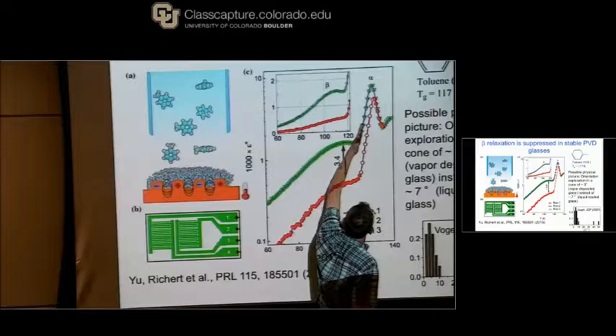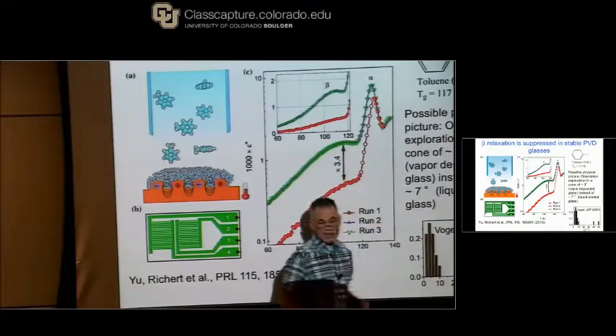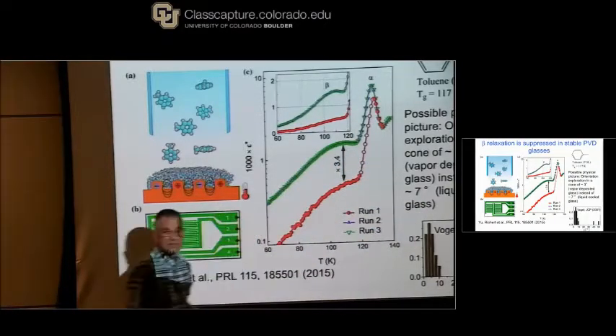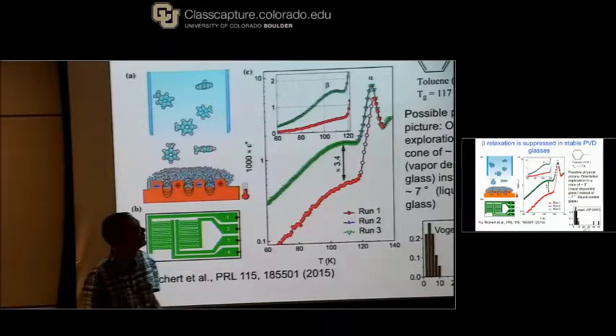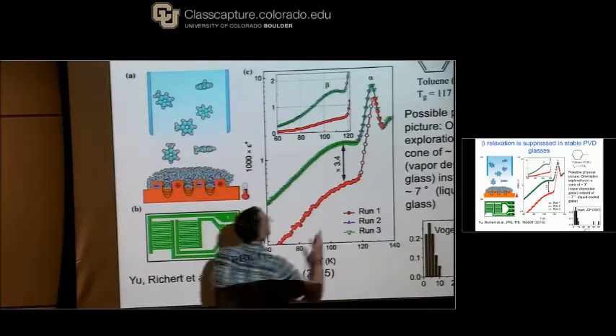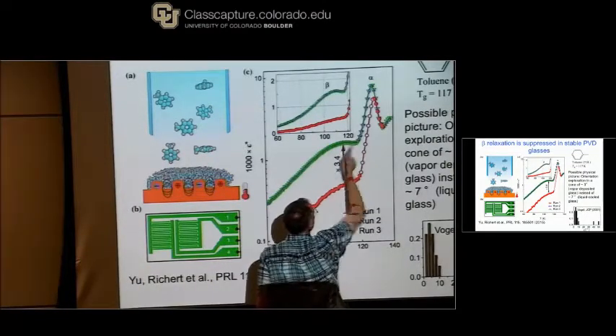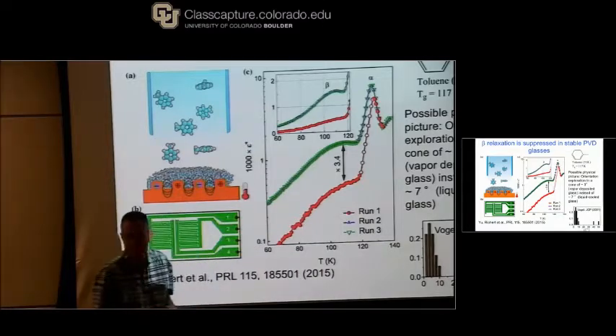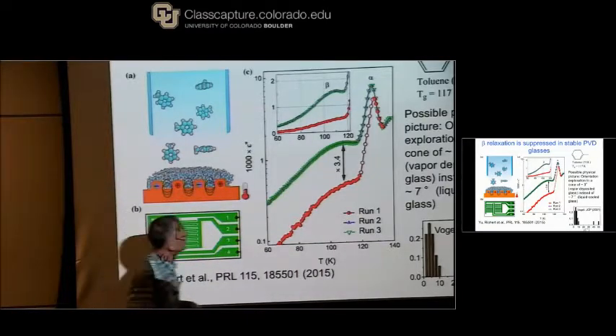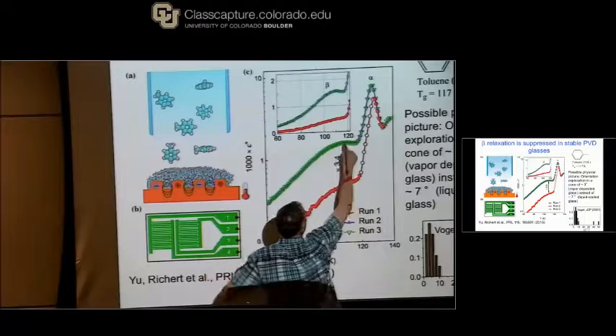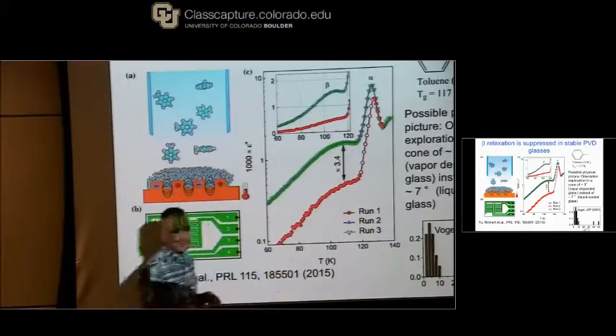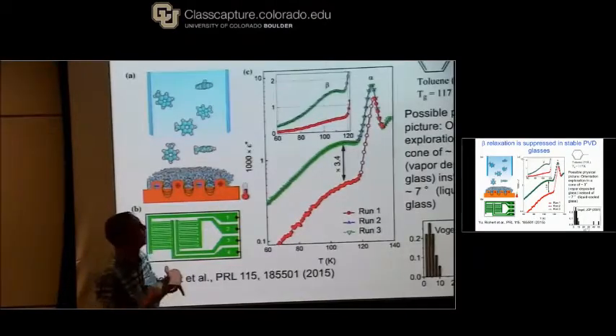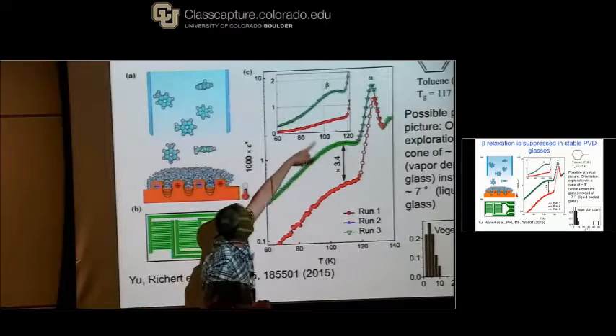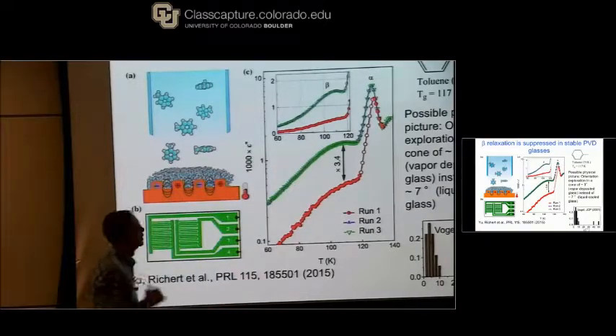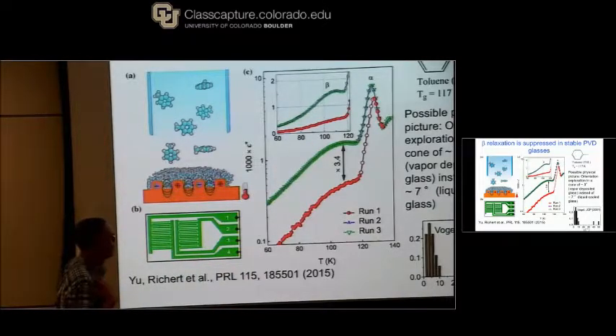And the fact that the stable glass joins the alpha process late is consistent with its kinetic stability, okay? But for our purposes, this is the interesting thing. This peak is the beta process in toluene. And this is a log scale. It's suppressed by a factor of 3.4 in a sufficiently packed glass. And if you want to see the data on a linear scale, you can look up there.